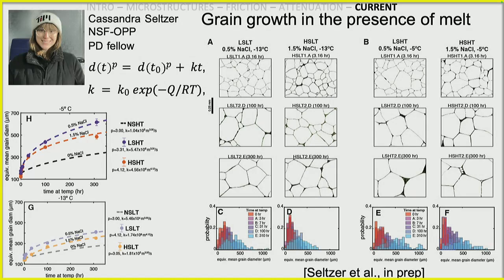And so we were looking through the literature, and we're actually really unsatisfied with the literature on how melt affects grain growth. So she actually had two undergrad interns this summer, and she had this very strict freezing, annealing, quenching time scale schedule for them. And they did a great job, and in just a few weeks over the summer, she's able to get this really nice study where you don't need computer methods to tell you that over 300 hours these grains grew. You can see it with the naked eye.